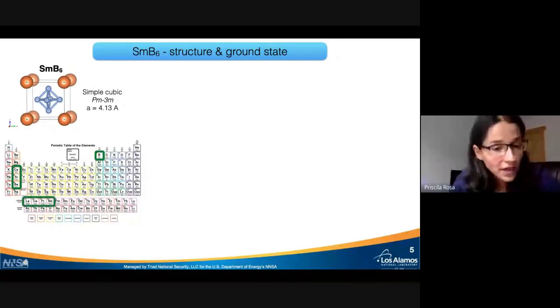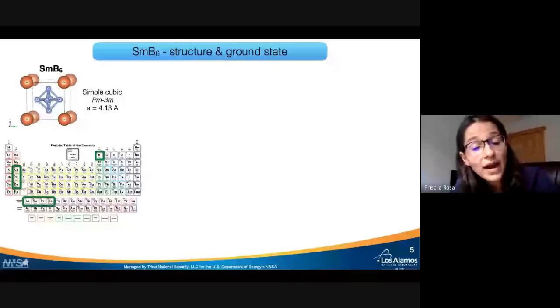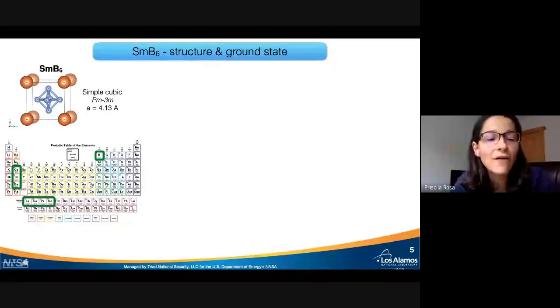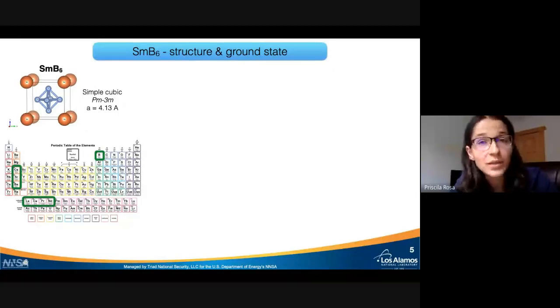But if we go over here to F electrons, so lanthanum, cerium, praseodymium, neodymium, they are all trivalent, so 3+. So they have 1 extra electron and the material is a metal. And for lanthanum, that's very beautifully seen in Hall effect data. You see exactly 1 extra electron per unit cell.